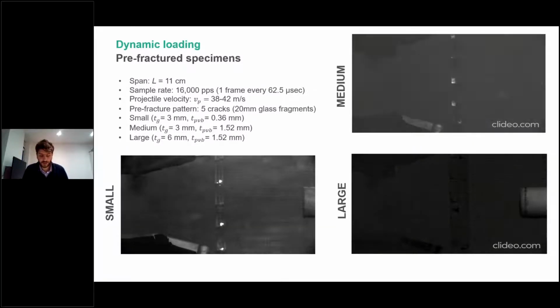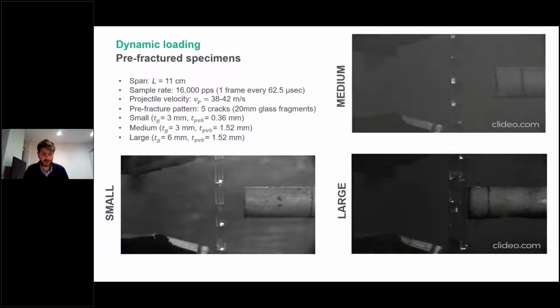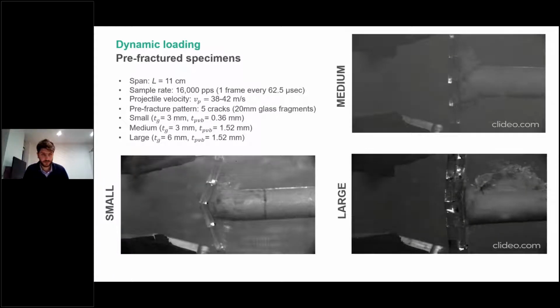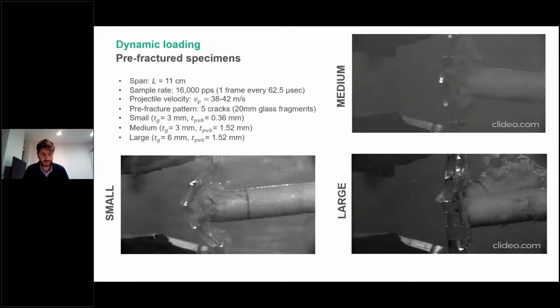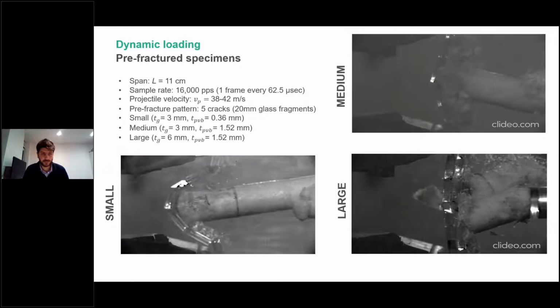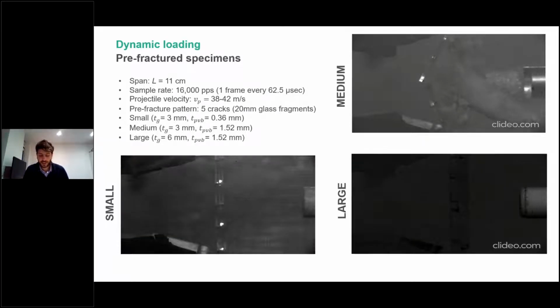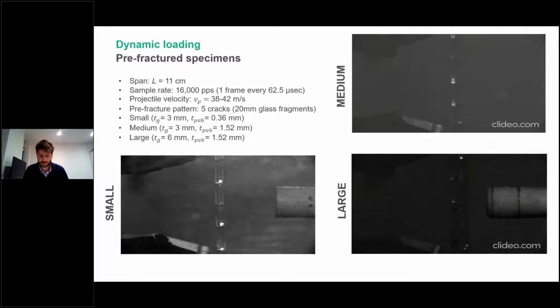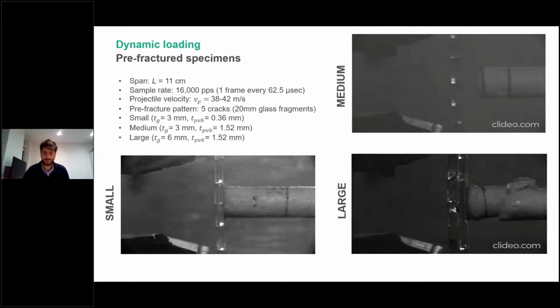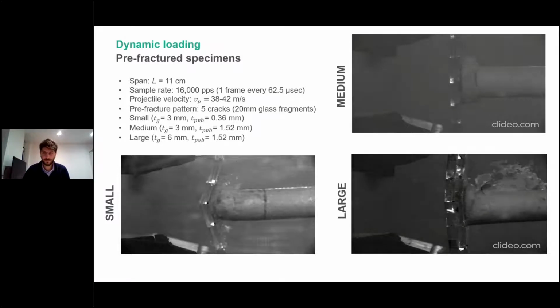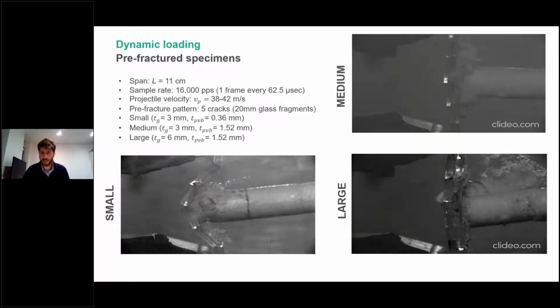PVB tearing was observed in the smaller cross-section specimens, as can be seen in the lower left video. You can see the tearing occurring right now. On the other hand, the medium and larger cross-section specimens were able to deform under large deflections without the interlayer tearing, as observed in the other two videos on the right-hand side.